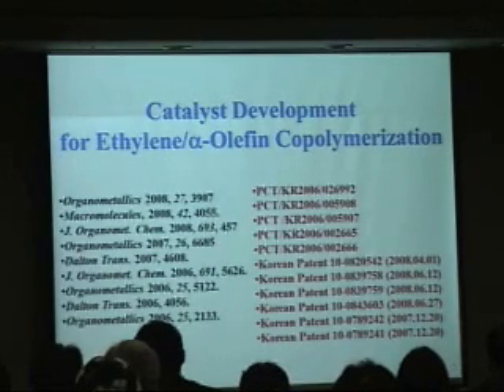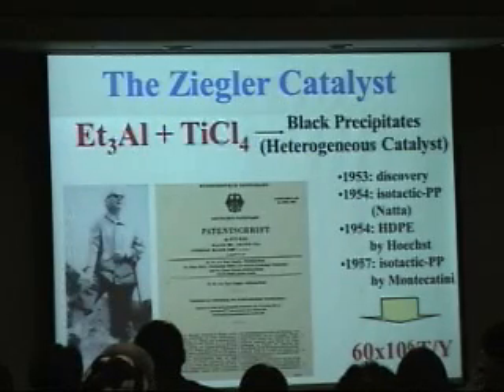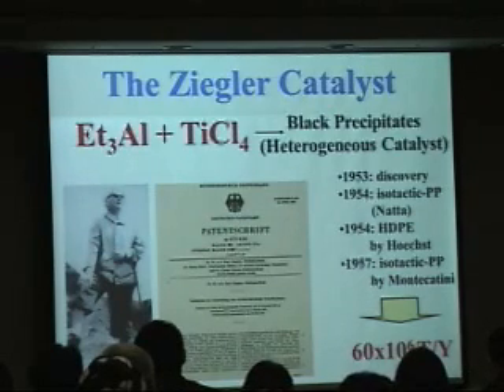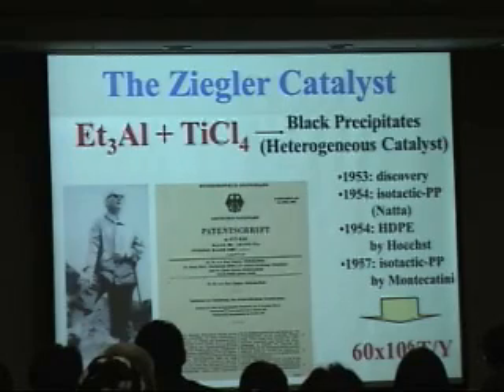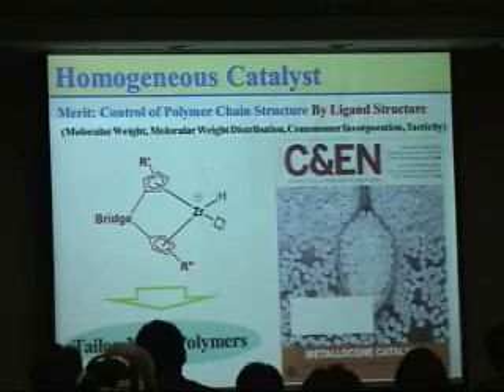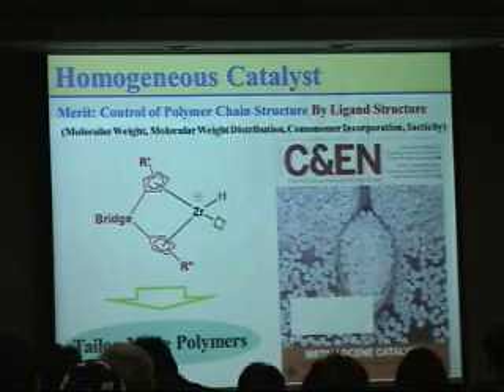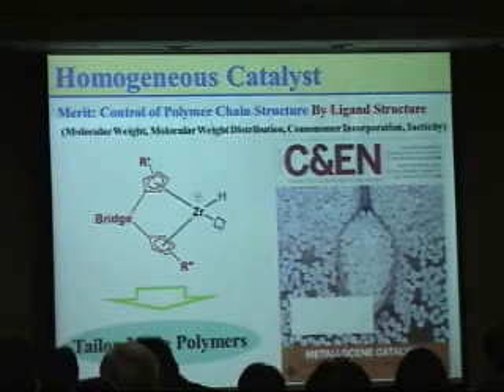So I would like to briefly introduce another success story, catalyst development for ethylene alpha-olefin copolymerization. A huge amount of polyethylene and polypropylene is now being produced by Ziegler catalyst. Ziegler catalyst is a heterogeneous catalyst prepared by mixing triethyl aluminum and titanium tetrachloride. And in the 1970s, the homogeneous Ziegler catalyst, which is called the metallocene catalyst, was introduced, and the merit of the homogeneous Ziegler catalyst is that we can control the polymer chain structure, such as molecular weight distribution and comonomer incorporation, by modulating the ligand structure. And I think more than 10% of polyethylene is now being produced by the homogeneous metallocene catalyst.